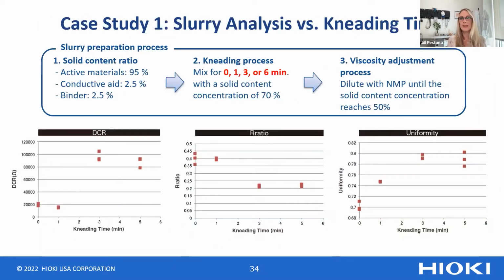And lastly, I have 2 case studies to share about this slurry analysis, because you're probably wondering, this sounds great, but have you actually demonstrated the technology? And yes, Hioki has demonstrated this technology. So the first study is looking at the difference in kneading times or mixing times of the slurry. So you have the same solid content ratio. You mix it for 0, 1, 3, or 6 minutes, and then you add NMP, the solvent, until the solid content concentration reaches 50%.